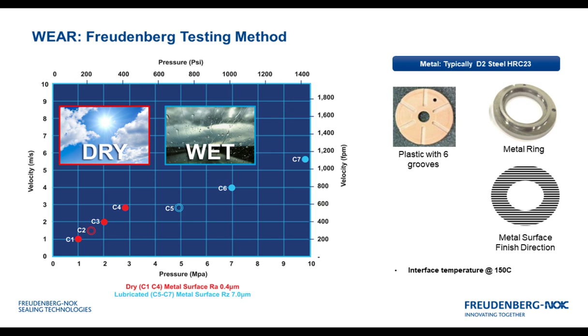The standard that we developed, the primary importance is to control temperature. The data I'm going to show you today will be temperatures at 150 degrees Celsius. That's our standard that we normally would test to. This test method uses a disc of material with 6 grooves. This is to eliminate debris from getting into the test condition to further reduce the noise and variation so we can understand what the materials are doing.